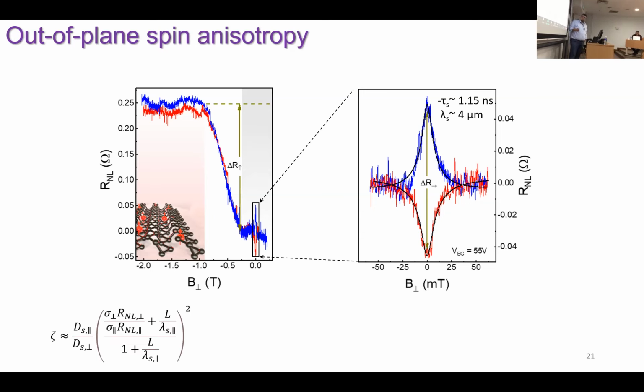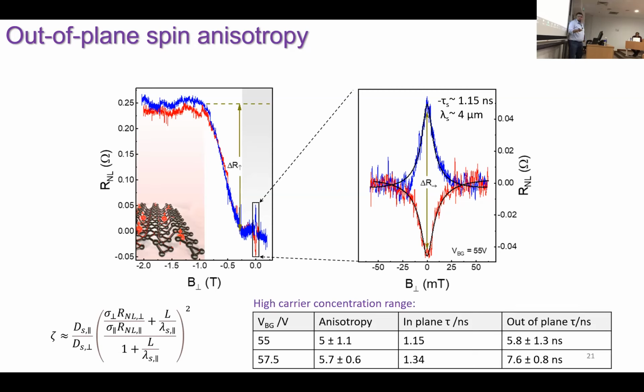And we did some simple approximations. And here, these are the values that we are extracting. For example, it depends slightly on the gate voltage that you apply, but we have a spin anisotropy around 5 to 6 in this material, meaning that the spins pointing out of plane have much longer lifetimes compared to the in-plane ones. At low temperature, in-plane spins have around 1 nanosecond for this sample. For out-of-plane, it's around 7 nanoseconds.